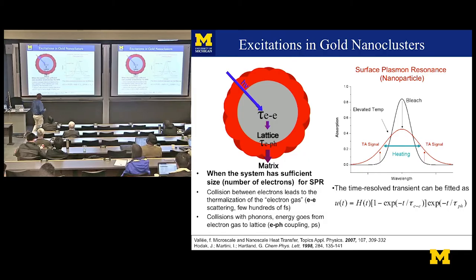So if you do the transient absorption kind of measurement, this is wavelength, this is absorbance. So here's the absorption peak of the molecule to begin with. And if this was just a surface plasmon particle, a big particle, it would have this big surface plasmon on here, and you would excite right in the surface plasmon, and you would see some bleaching of that surface plasmon. And if that bleaching happens, then you would see that the wings now look a little bit bigger, okay? So this so-called time-resolved transient absorption experiment was used as a measure of how much the system absorbed the photon and then how much excited state absorption happened.